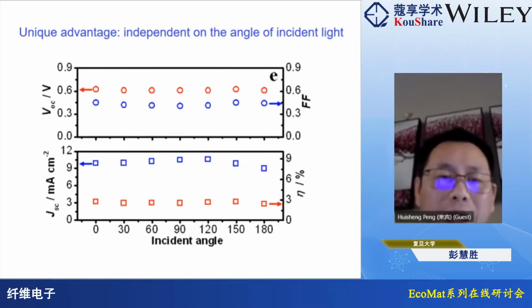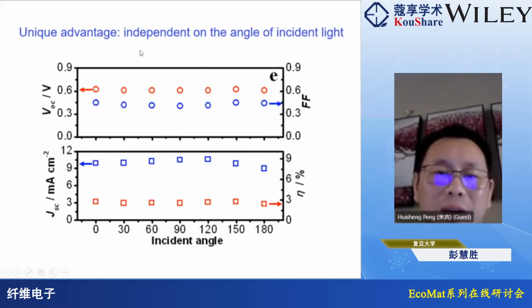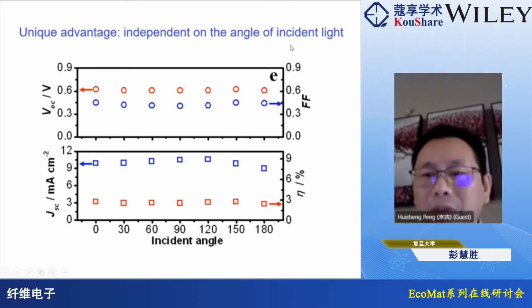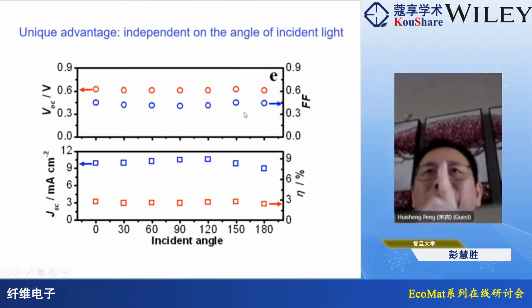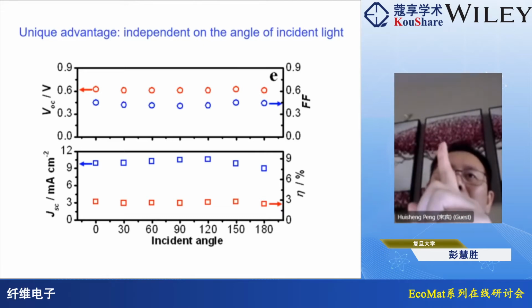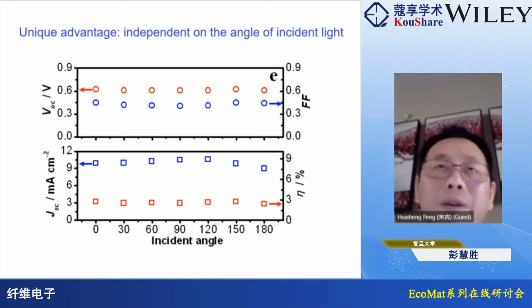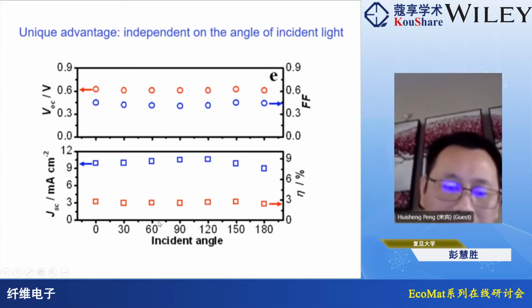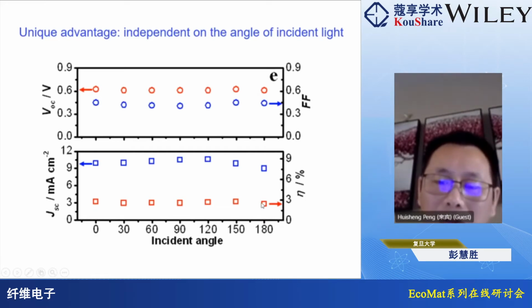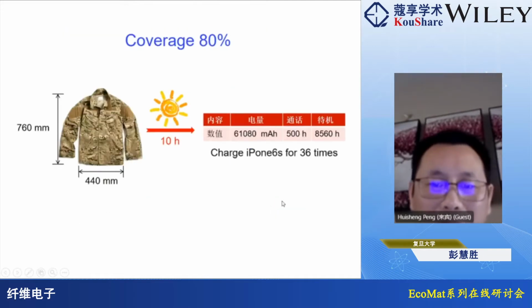And for the fiber solar cell, there is also another very interesting advantage. The power conversion efficiency is independent of the angle of the incident light, because it's one-dimensional, and when the light is emitted from different directions, you can expect that the illuminated area is very stable. So we see that the incident angle changes from 0 to 180 degrees, and the power conversion can be well maintained.